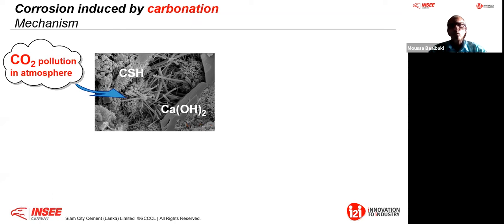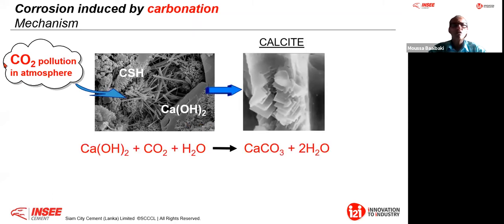This Portlandite will combine with the soluble CO2 that comes into your concrete and form calcite. This is what I say: this is leachable, this is soluble. Therefore, if this happens, don't clean it. Leave it. Aesthetically, it's not nice, but leave it, because it is stabilizing the pH. It keeps your concrete microstructure at a pH level where it is basic, and therefore the reinforcement is protected.